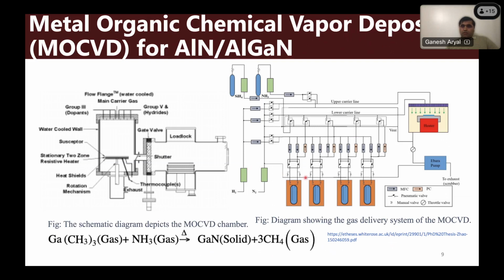That hydrogen carries the precursors into the chamber, whereas ammonia also flows into the chamber, and there is a chemical reaction. The precursor reacts with ammonia at high temperature, which helps to form gallium nitride and some other compounds. The other compounds are exhausted through the pump, and the gallium nitride, aluminum nitride or other compounds grow on the sample.